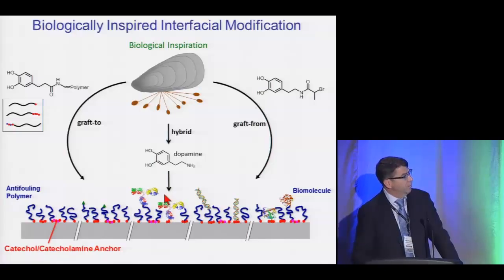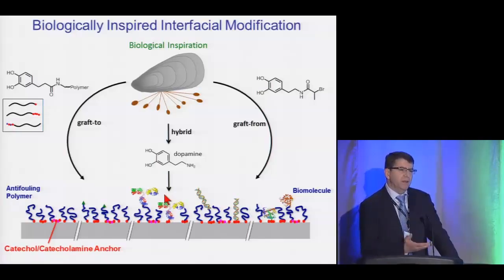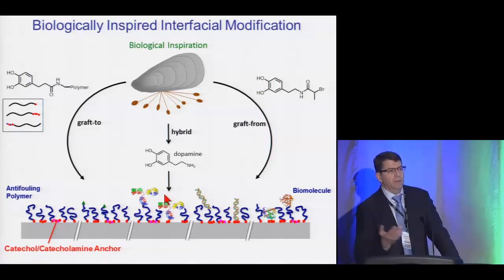a catechol derivatized polymer or a catechol initiator, which bonds to the surface, and then we can therefore functionalize surfaces using catechol as an adhesive chemistry, maybe in the same way that you might use a silane on a metal oxide, or an alkane thiol on a gold surface, except these are tremendously more versatile than those other chemistries. Those other chemistries are very, very precisely tuned to one type of substrate. And the catechol works on most substrates, actually.